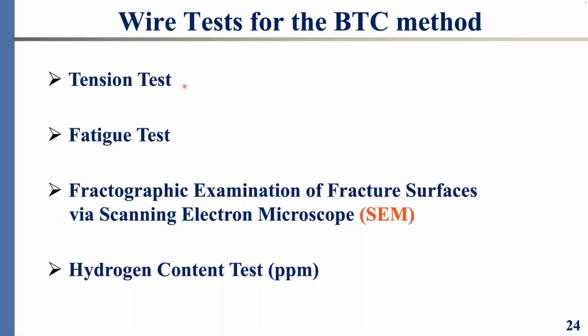The BTC method, because we are very keen and very watchful of the cracking conditions or the cracked wires in the cable, we like to know where they are, and to what extent of cracking the wires are going through. It's very important for the accurate assessment of the strength with measurable metrics, as we're going to see later on. So we do fatigue tests, and we do fractographic examination of the fracture surfaces to identify pre-existing cracks. Remember I mentioned that the wire is 5 millimeters in diameter, so it's a very small component, and we do the fractographic examination via scanning electron microscope. Thus, it's dubbed as SEM images, as I'm going to show you later on.